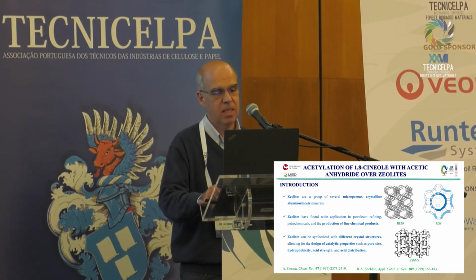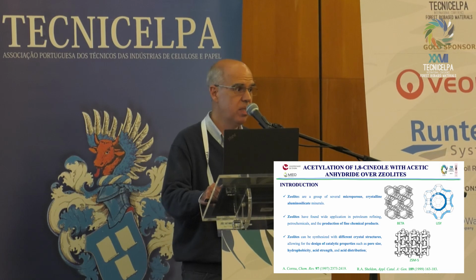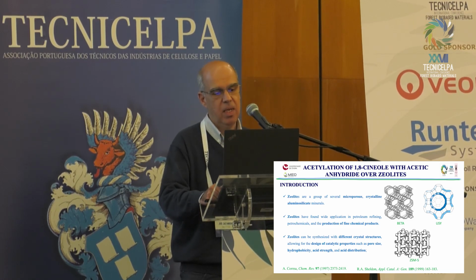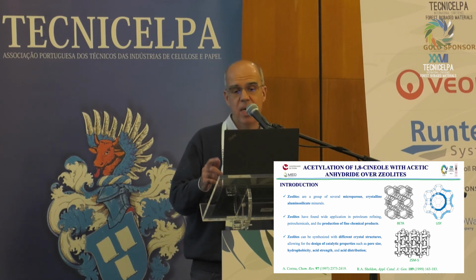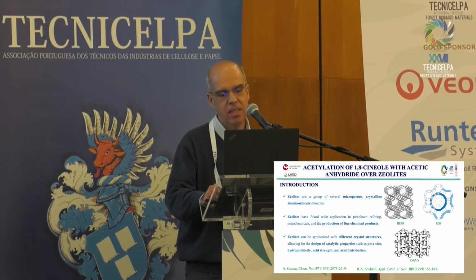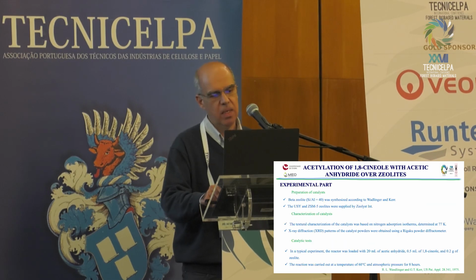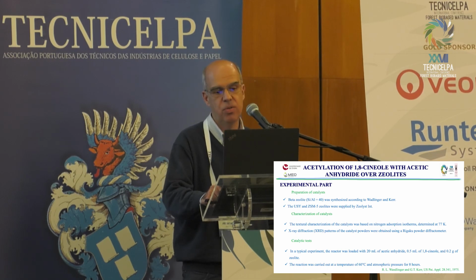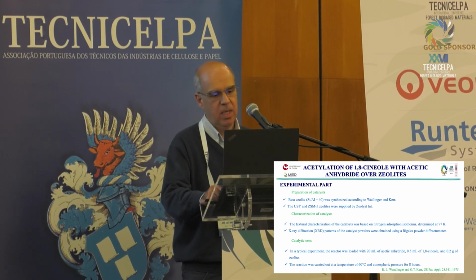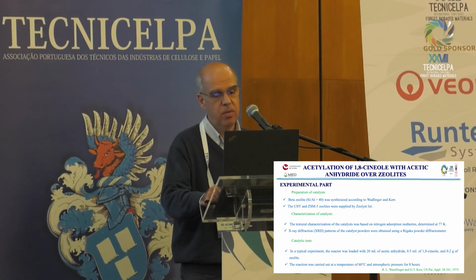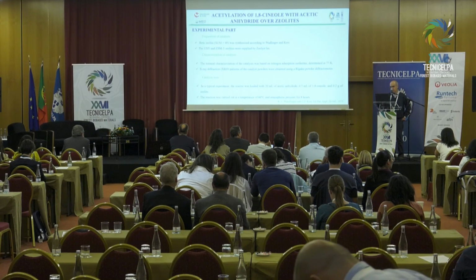Zeolites are crystalline aluminosilicates. These zeolites can be used as catalysts in the petrochemical industry and fine chemistry. The zeolites used are beta zeolite, USY zeolite, and ZSM5 zeolite. The beta zeolite was prepared in the lab by my students, and the other zeolites were supplied by zeolite suppliers. This work is in the beginning. The catalysts were characterized by nitrogen adsorption isotherms and X-ray diffraction. In the reaction, the reactor was loaded with acetic anhydride, cineol, and zeolite. The reaction was carried out at 60 degrees.